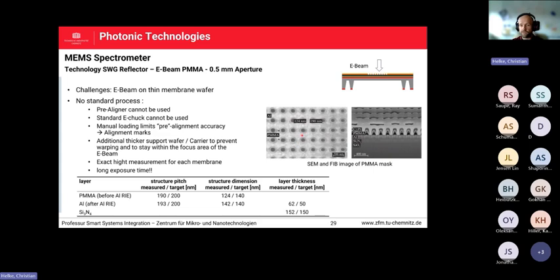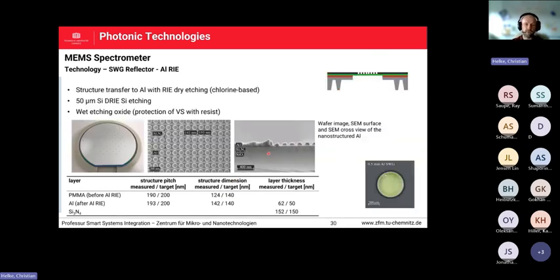These black dots are the PMMA resist with a pitch of 190 nanometer. If we look at this table here, we have 190 nanometer with a pitch of 200 nanometer and 124 nanometer to 140 nanometer, not far away from the requirement from the simulation point of view. And we decided to go further, meaning that we etch the structures into aluminum afterwards, which then acts as the reflector on the thin silicon nitride membrane of here 150 nanometer thickness.